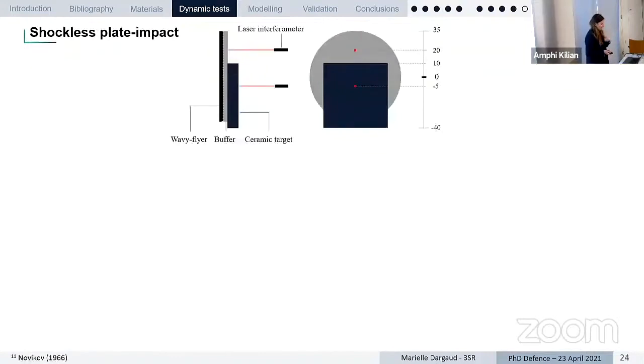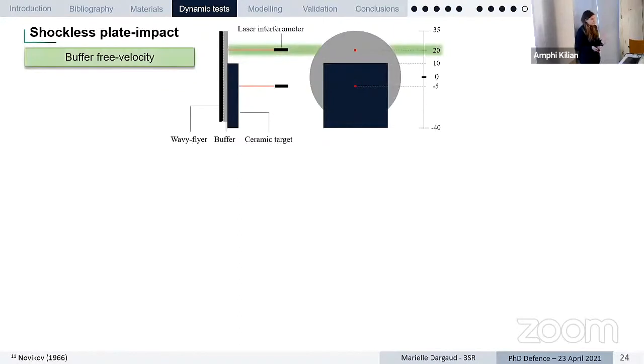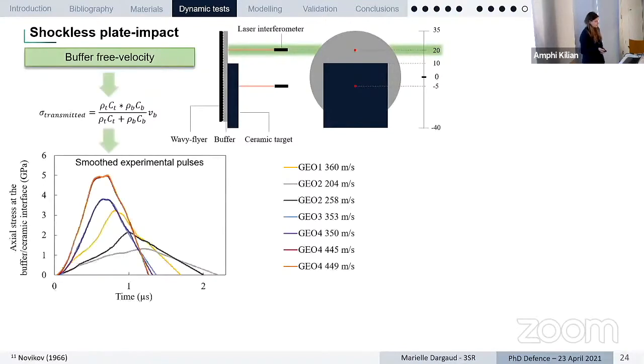So here you have a scheme of the setup where you have the fly plate, the buffer, and the ceramic. We've decided to translate slightly the ceramic according to the loading direction to be able to use a first laser interferometer at the rear face of the buffer plate. By using this laser and some post-processing, we are able to evaluate the buffer free velocity. This information can be converted into a transmitted stress, which is going to be transmitted to the ceramic.